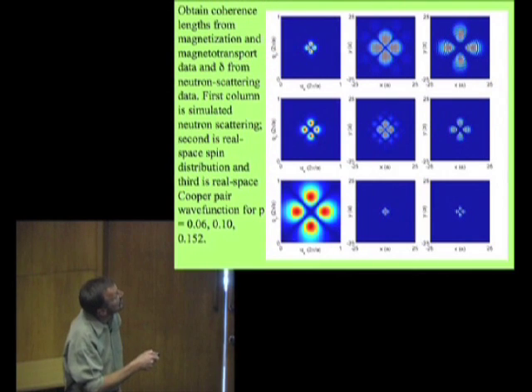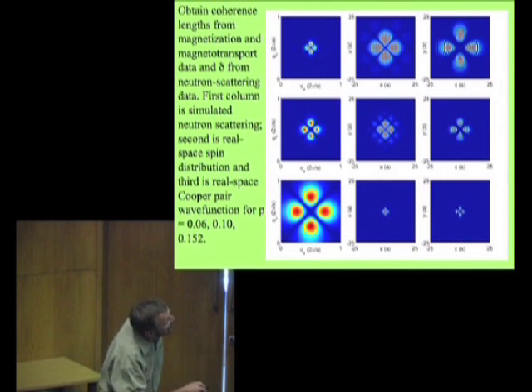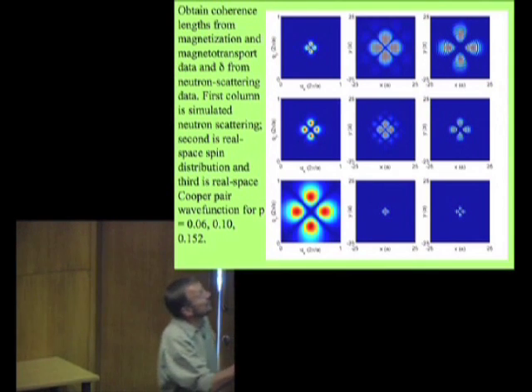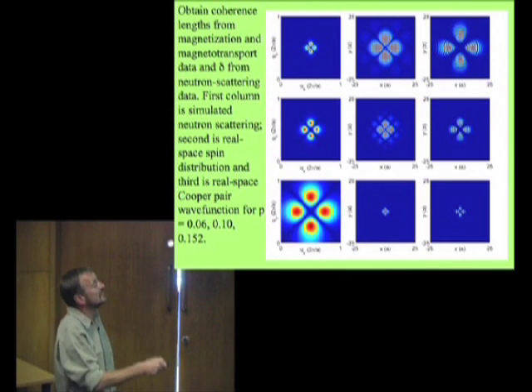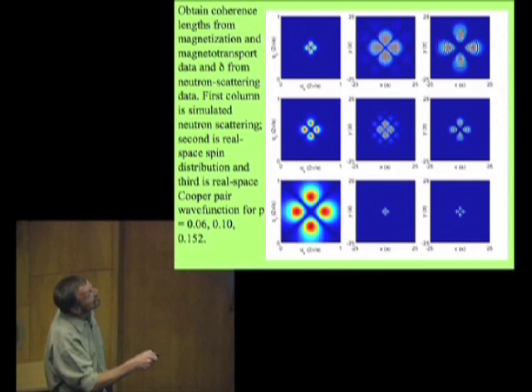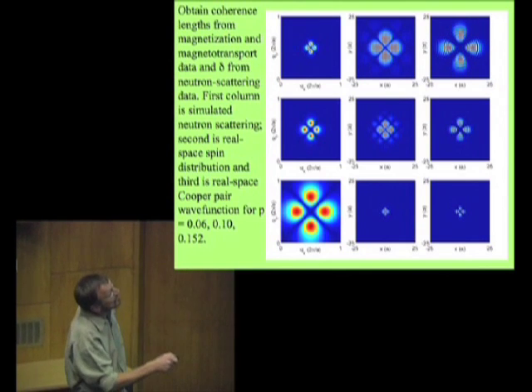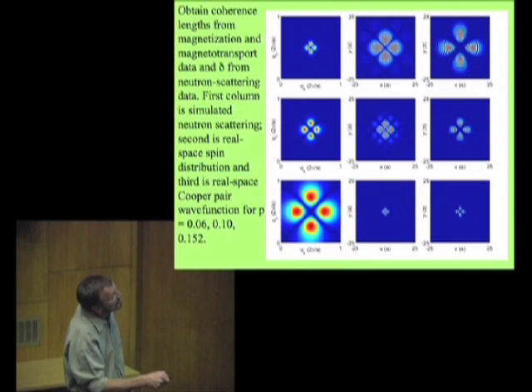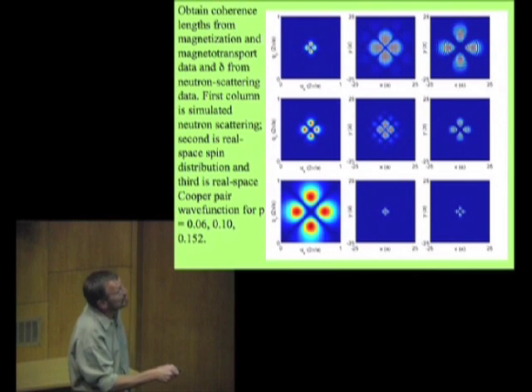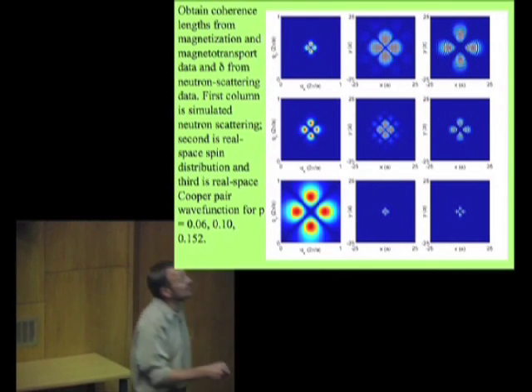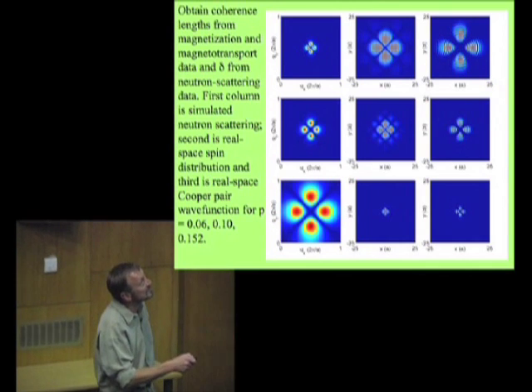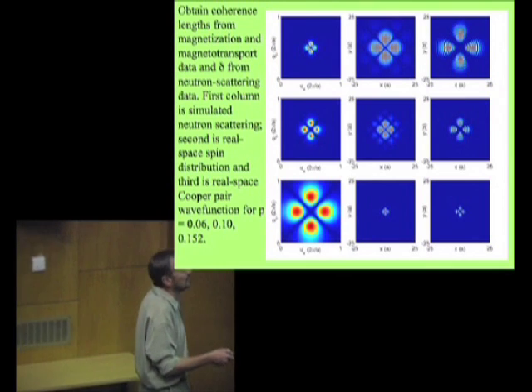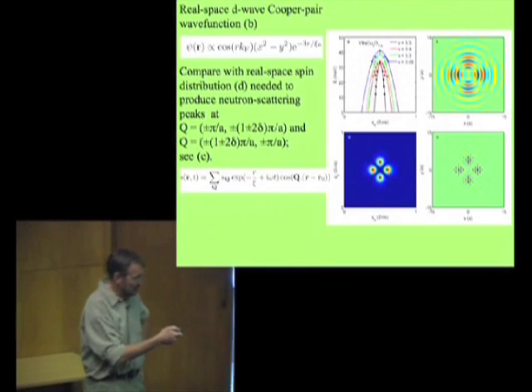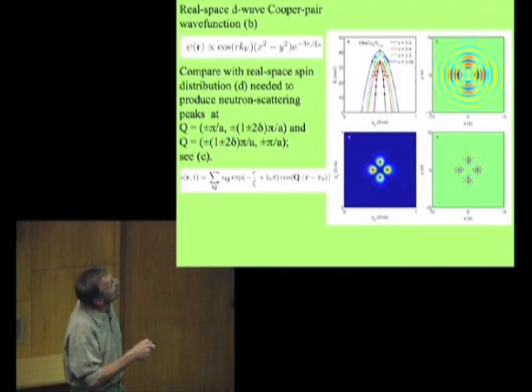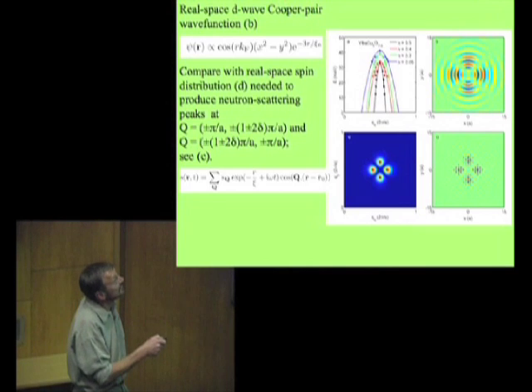This is 0.06, 0.10, 0.152. These are neutron scattering data, or inferred from neutron scattering data. These are the Cooper pair wave functions plotted using thermodynamic measurements of the coherence length. And you can see that with no adjustable parameters, these things match very well. As you increase the hole doping, the Cooper pair wave function gets smaller. As you increase the hole doping, the spin susceptibility distribution gets smaller as well. And these things match up rather well. Remember that the data that went into drawing this are completely independent of the data that went into drawing this. And these are for these 3 separate dopings. So if you look at these 2 representations here, you can see that the length scale of this one is given very much by the coherence length.